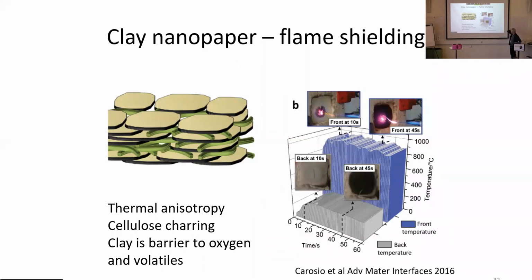And if you look at the flame shielding properties, so this is a film which is only 100 micrometers in thickness. You put a torch on one side, and you end up with a temperature which is approaching 1000 degrees. And for 1 minute, the temperature on the other side, 100 micrometers, is below 200 degrees. So this is really remarkable. The explanation is thermal anisotropy because of the platelet organization. Cellulose has very unique properties when it's combined with clay. So it chars and forms an insulating layer. And also, the clay functions as a barrier to oxygen. So this slows down the burning process. It prevents volatiles from escaping and feeding the flame. So this is one example of how you can functionalize cellulosic materials by using the small-scale structure.